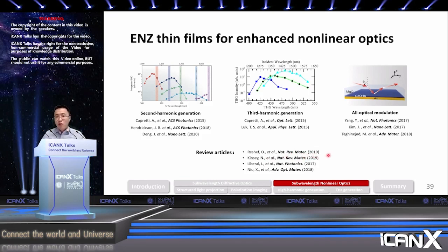Okay. But one of the questions that we have been asking is that although we know that this ENZ material can be used to enhance the efficiency of second harmonic or third harmonic generation, right? But we also know that for all those bulk nonlinear crystals, nowadays they can achieve a harmonic generation efficiency of maybe 50% or even higher, right? Although this ENZ material can be used to enhance the harmonic generation efficiency, the number is still on the order of 10 to the minus 5 or 10 to the minus 6. Okay. So with such a low generation efficiency, how is it possible to be useful?